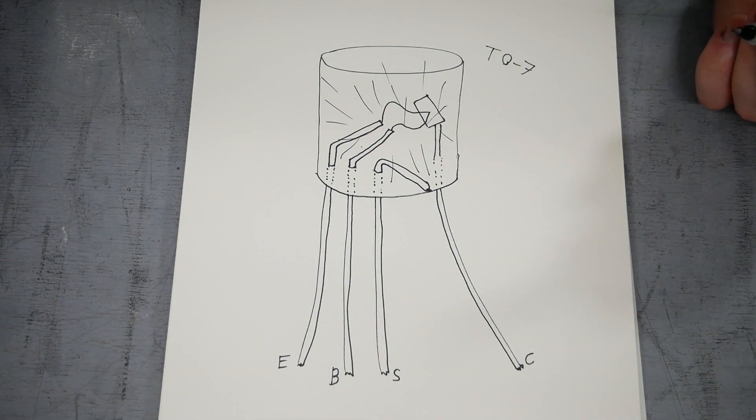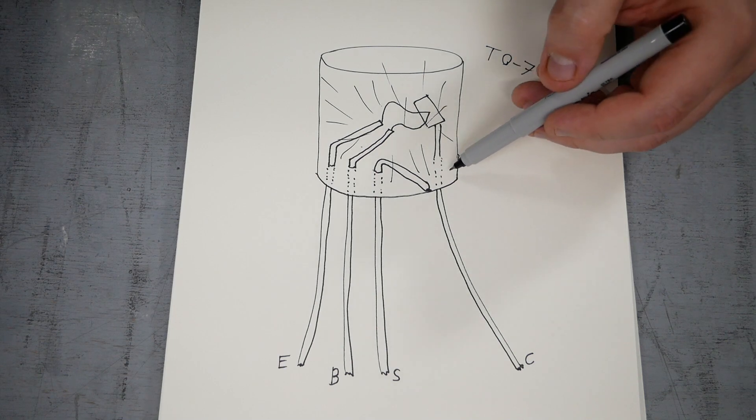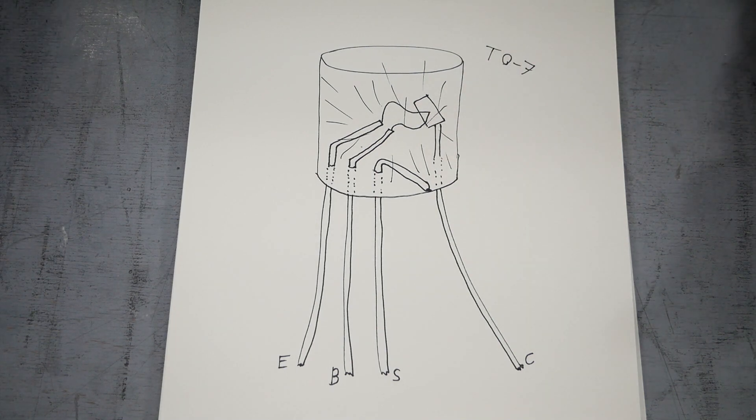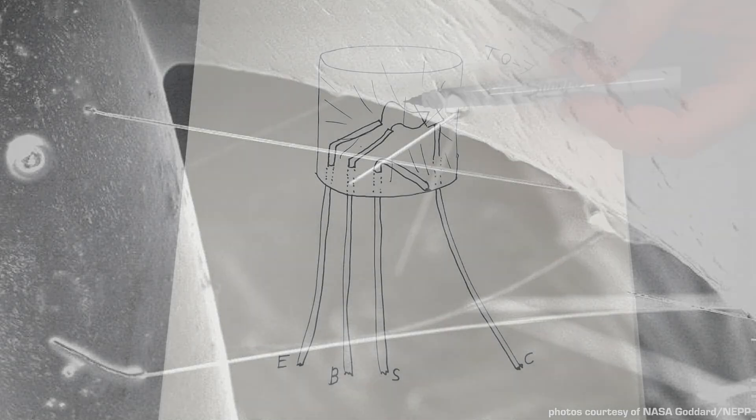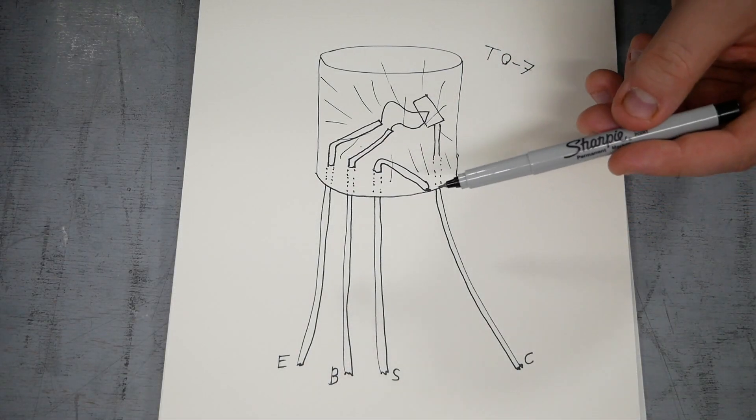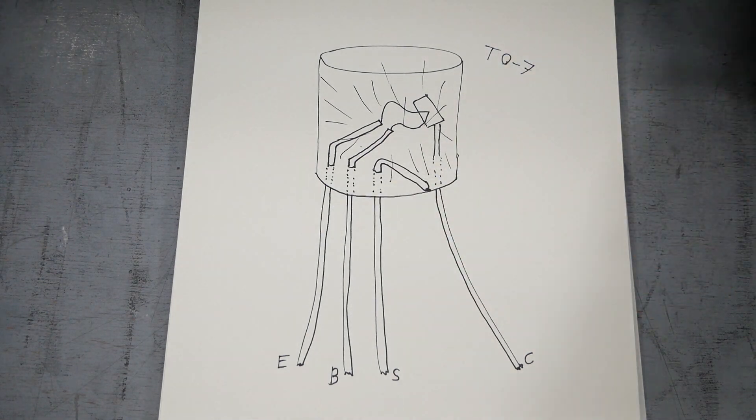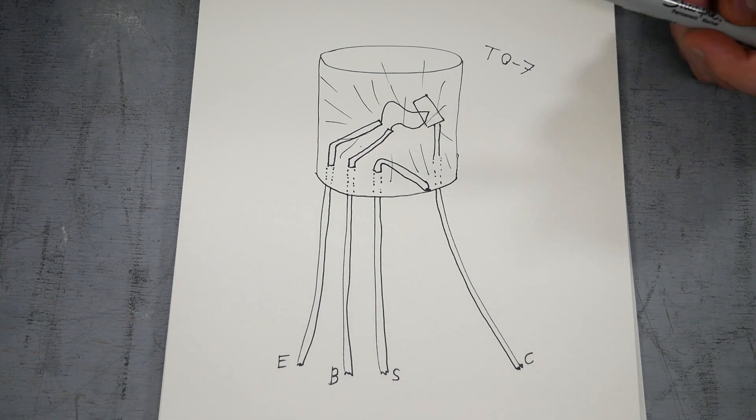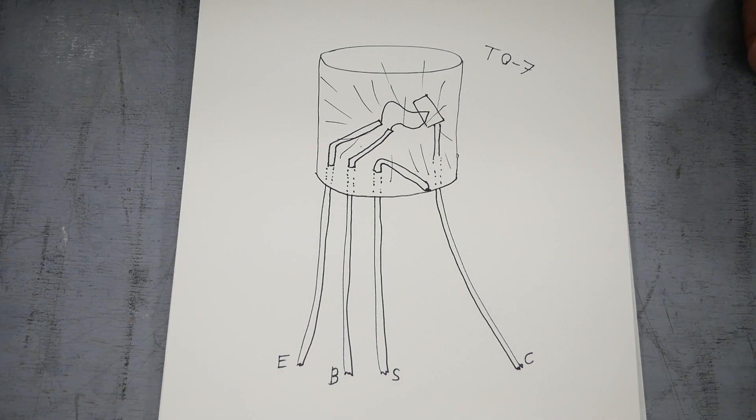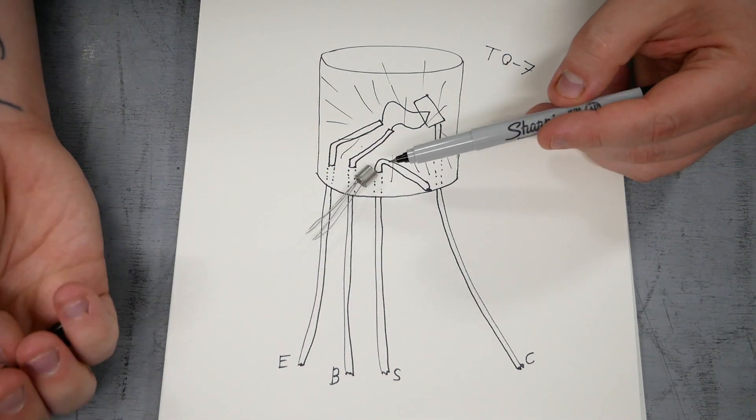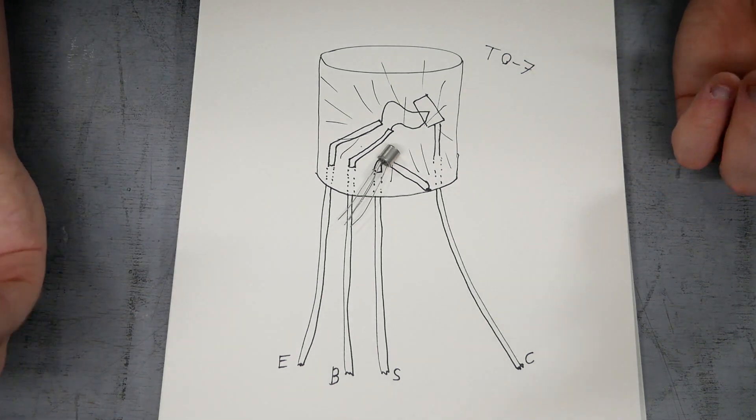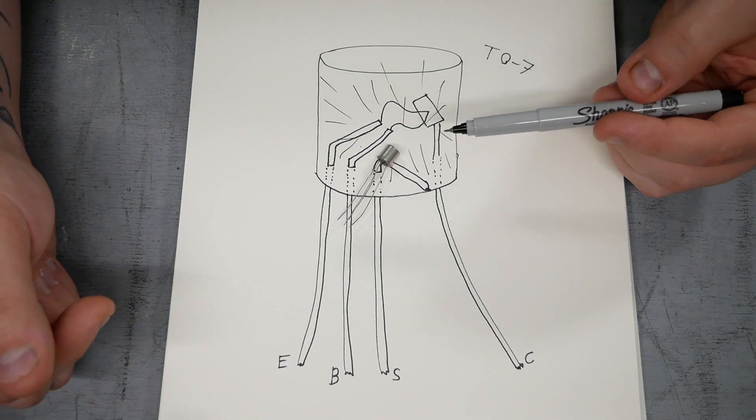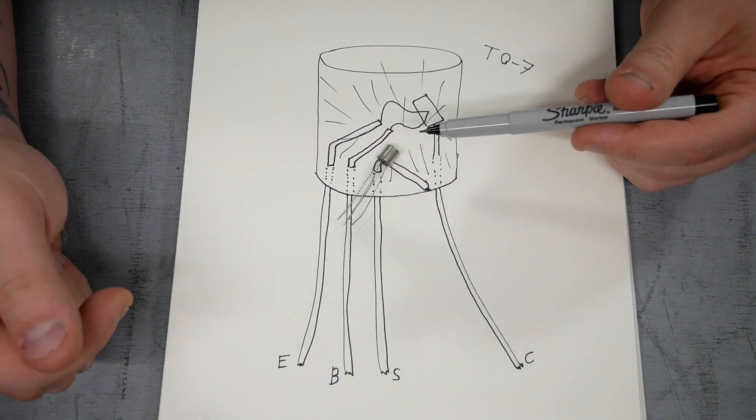These hairs are exceptionally thin. We're talking like a few micron. Your hair for comparison is about 70 microns. So significantly smaller than a human hair, but they are conductive and they can cause a shorting path between the case of the transistor and one of the electrodes of the transistor. They also can short two separate electrodes at the same time, therefore essentially causing a circuit between two electrodes. They short together.